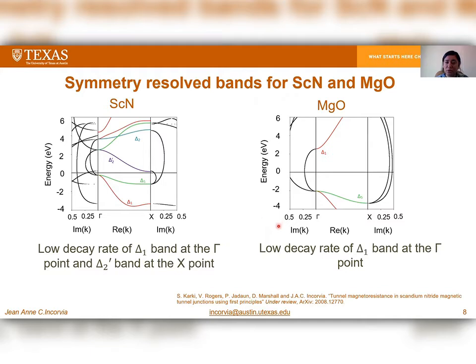In parallel, we also did our symmetry resolved bands for MgO, and as expected, we see a low decay rate of the delta 1 band at the gamma point. All of our calculations are done in parallel with MgO so that we can validate our results for scandium nitride. If you want to look at more detailed work, this is our paper on tunnel magnetoresistance in scandium nitride magnetic tunnel junctions using first principles, which is under review at the moment.